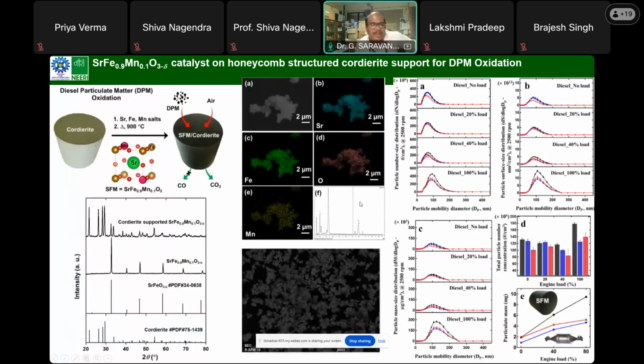So once we realized that it has potential, we developed a prototype for a typical automobile exhaust using a cordierite substrate. We coated this manganese substituted strontium ferrite, loaded it, and checked the catalytic performance using an actual engine dynamometer. This is a collaborative work with IIT Kanpur.